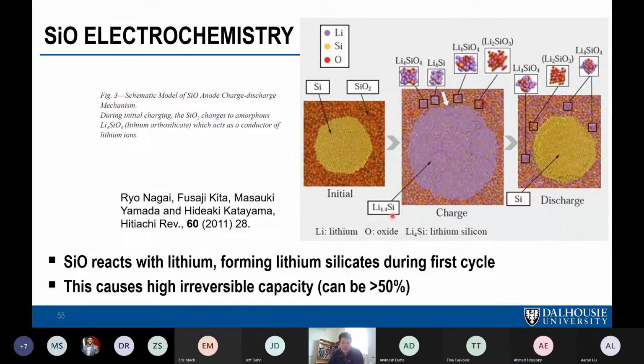And here they put lithium 4.4 silicon, but you really get lithium 15 silicon 4. And then this is reversible. For this phase, you could take the lithium out. For the Li4SiO4 phase, the lithium is basically stuck. For any commercial cell where the potential of the negative electrode doesn't generally go above a volt, if you go above 1 volt, you can take the lithium out of this, but in a commercial cell, you wouldn't have the negative electrode going up that high. So this lithium essentially becomes stuck and inactive and results in a high irreversible capacity, and that irreversible capacity can be higher than 50%.